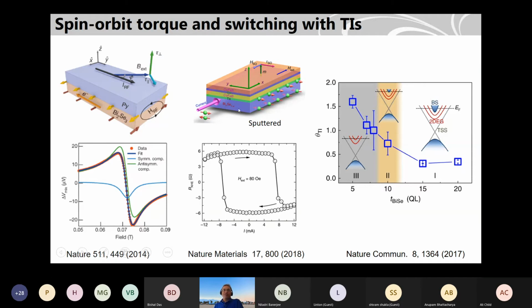So the magnet on top of this topological insulator, they could switch with very low current compared to what we can do with platinum or tungsten. So this is quite useful for industrial application because it can be deposited by sputter deposition. I just mentioned that it may not be a topological insulator, but this material helps to get high spin to charge conversion. And people have also seen how to tune it by different topological insulator thickness. They can see the spin Hall angle is very large when you go to very thin samples.